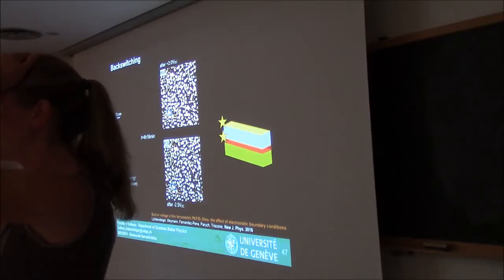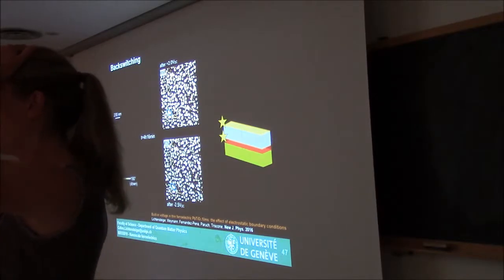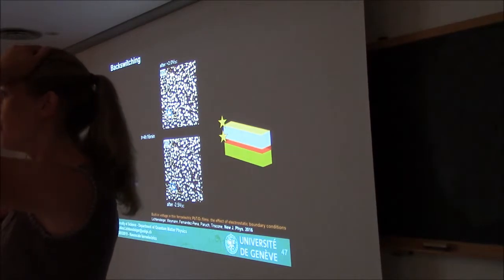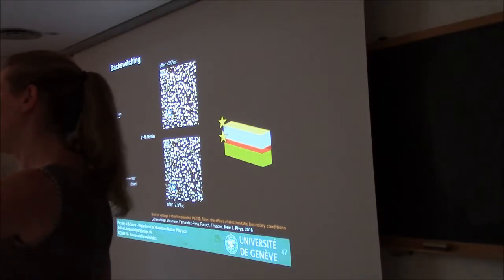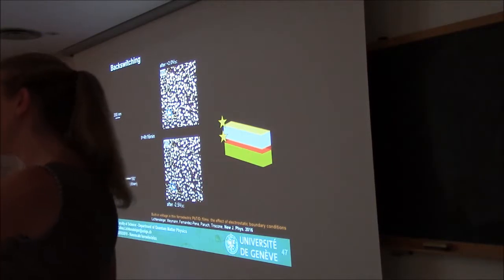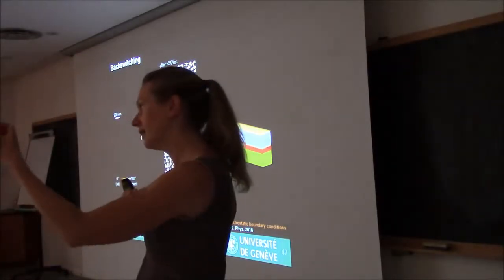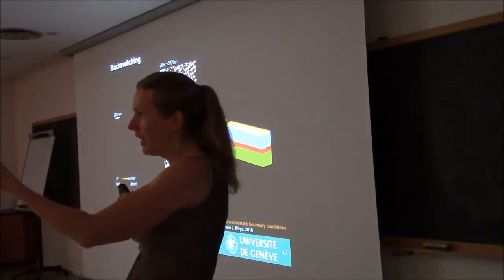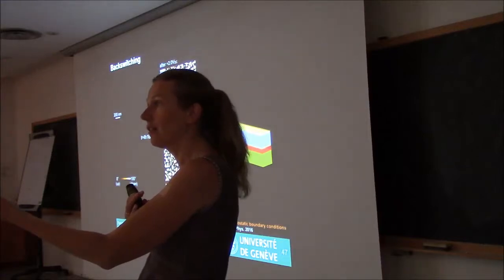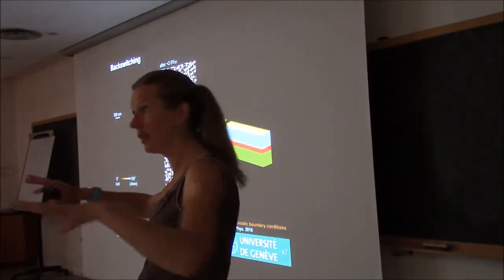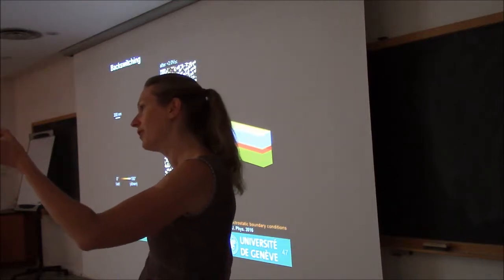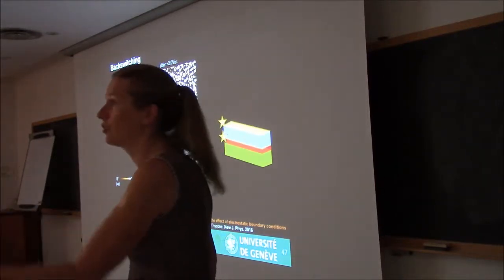What is very interesting is that when it does switch back, the domains always reappear first at the same position. So it seems that intrinsically in the material there are some places where you probably have a different built-in field. I think that locally the built-in field is not homogeneous, and so there are some regions where it's more favorable to start, and it will start to switch more easily.